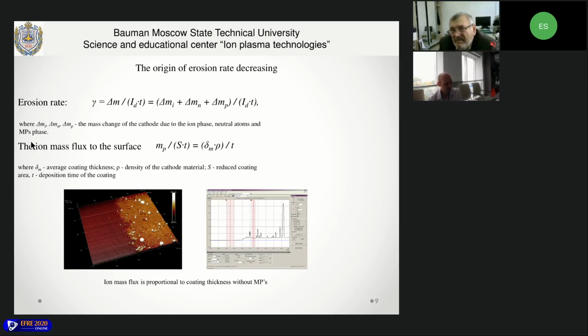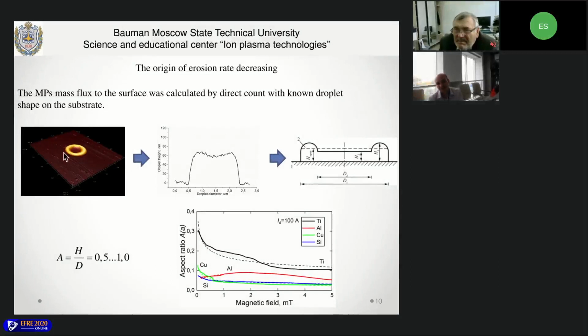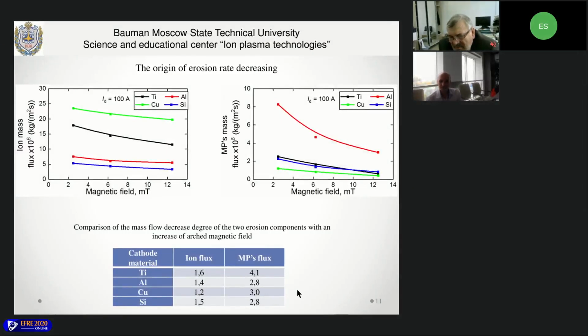Next, we can estimate the mass flux from the macroparticles. So we can know the macroparticles' form. The macroparticles' form is like a disk or maybe a hemisphere, and we can calculate the shape parameters, such as aspect ratio, which is height divided by diameter. And when we obtain this shape characteristic, and with known size distributions of macroparticles, we can obtain the mass of macroparticles, the mass flux